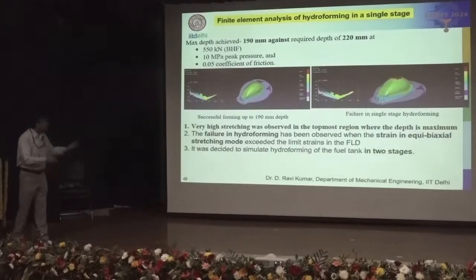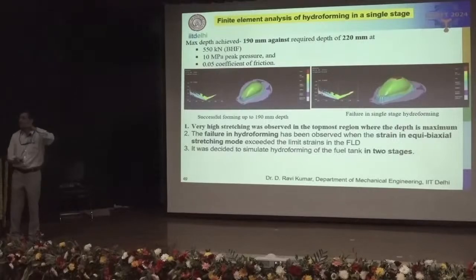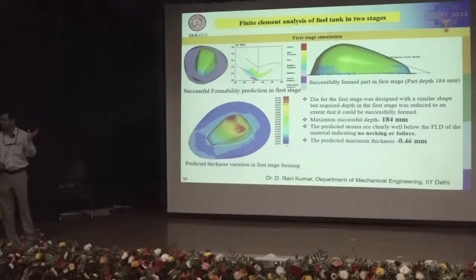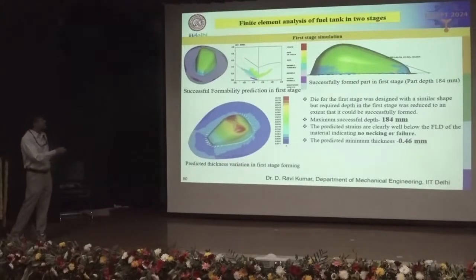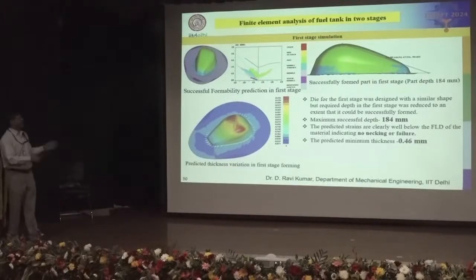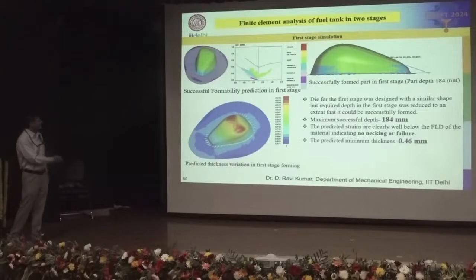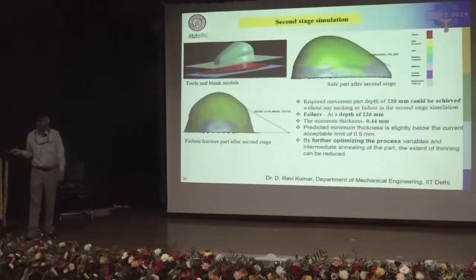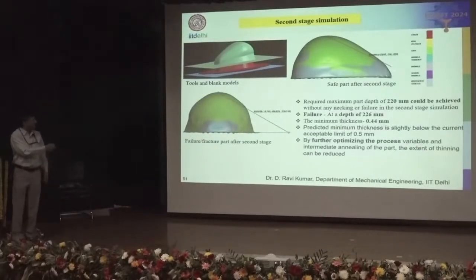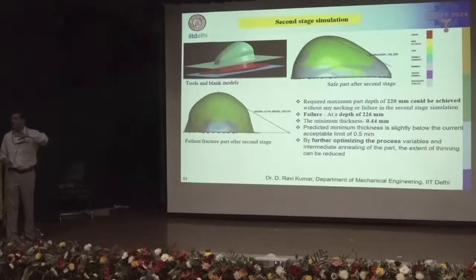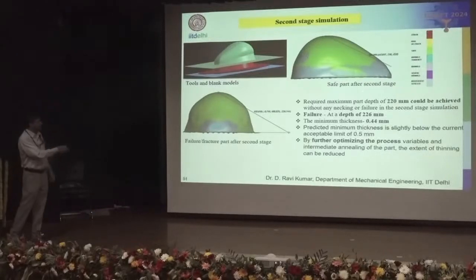So the material gets stretched equally in both the directions. And since we were unable to form the entire depth in one single stage hydroforming, we have gone for two-stage hydroforming. In the first stage, we were able to form up to 184 mm, and then this simulation data has been imported as the initial starting data for the second stage. And in the second stage simulation, we could successfully form the fuel tank up to the required depth of 220 mm.